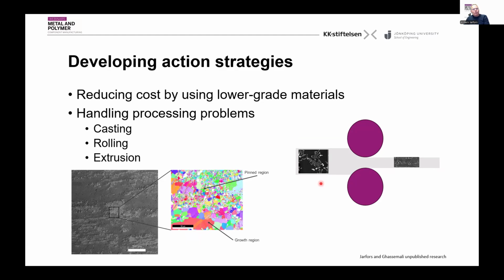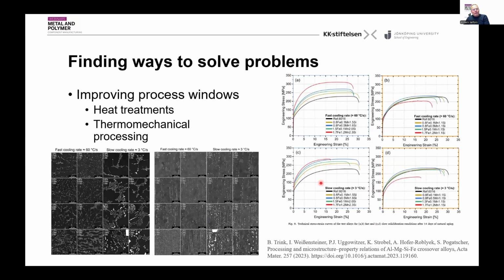So I think that we can go to the next. Now, this is another study that we found during the project, where you have the links between the cooling rates in the casting process and what happens when you roll these materials later on. And I think what is important here is to look at the tensile curves. If you take the lower right curve, you can see that the red curve is showing a reasonably high iron content and a manganese content, and it has a significant